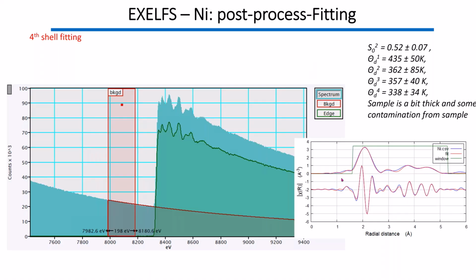Okay, so for each spectrum, in order to get a high enough SNR, you end up having to acquire on the order of minutes, something like 3 minutes roughly. It's hard to really argue that because it also depends on the sample thickness. You have to have the best sample thickness as well. So sometimes we use more, sometimes less. Also, when you have a very thin sample, it's not very good either, because of the signal. So it's hard to make a single comment on this.